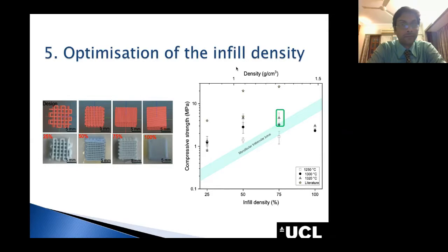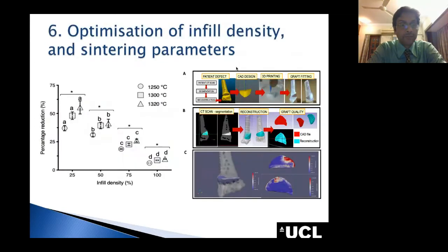And then the optimization of the infill density is also really important. We saw the difference between 25% and 100% infill density and compared that with the compressive strength of the mandibular trabecular bone found in the literature. We saw that 75% infill density with a sintering temperature of 1,320 degrees for 5 hours was in the range of the majority of the studies in terms of compressive strength and density.